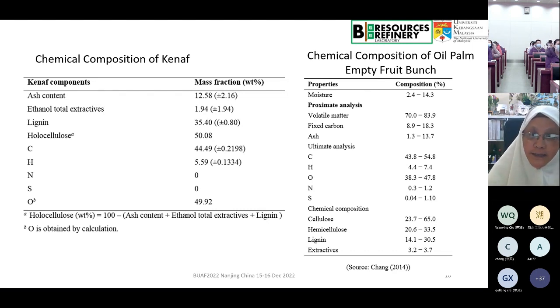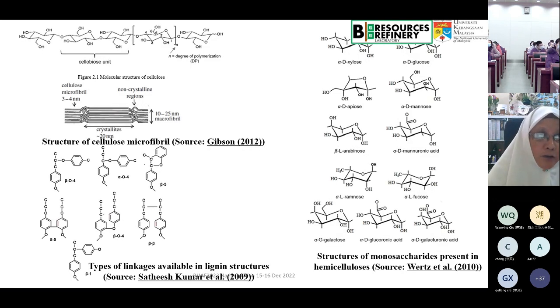So if you're talking about cellulose, then it's very good to convert these cellulose materials into high value added products. And the lignin from EFB and the lignin from kenaf are totally different, because lignin in EFB has a much higher proportion of the S syringyl unit compared to the one in kenaf. And we know that cellulose has a crystalline and also an amorphous region. So if you want to do any chemical modification, you have to disturb the crystalline area to make it more amorphous. And you can dissolve cellulose by separating the microfibrils among the cellulose chains with a certain solvent, and then regenerate it back to form another kind of cellulose.